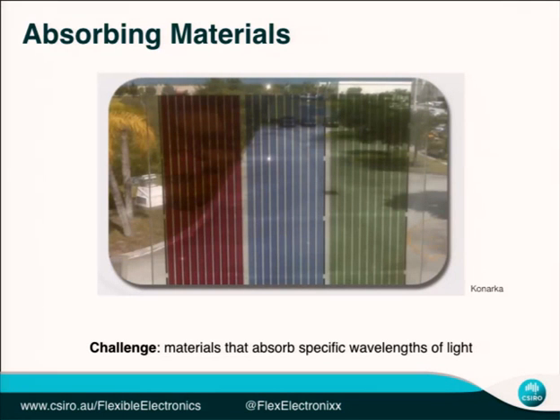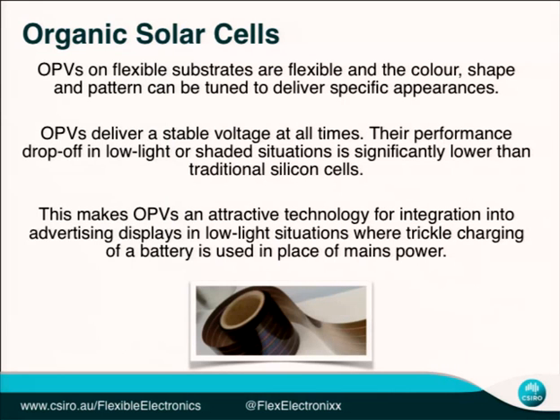So put together the fact that they're thin, flexible, and that we can change the way that they appear, we think makes them a valuable technology for a range of applications. Another aspect of them is that they do give a fairly stable voltage under low light conditions, unlike crystalline silicon that drops off very rapidly indoors or in shaded conditions. So that's a differentiating feature. And so you can possibly put them in situations where you just want to constantly charge a battery.